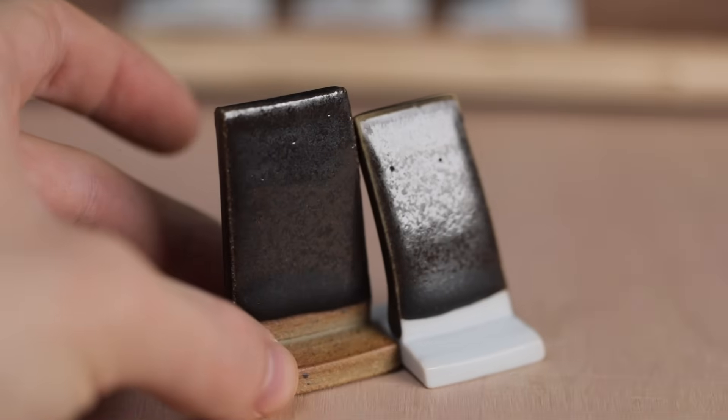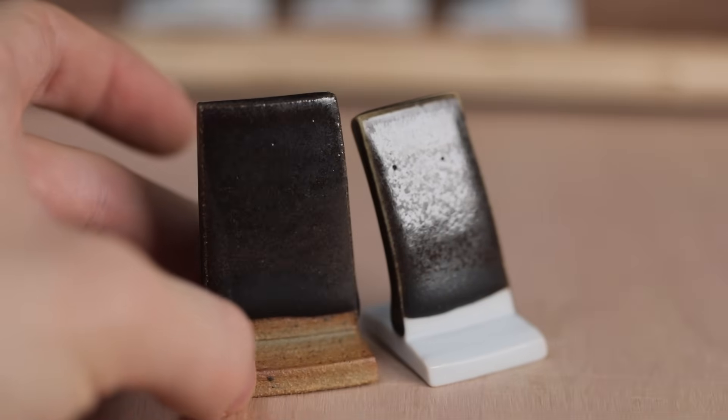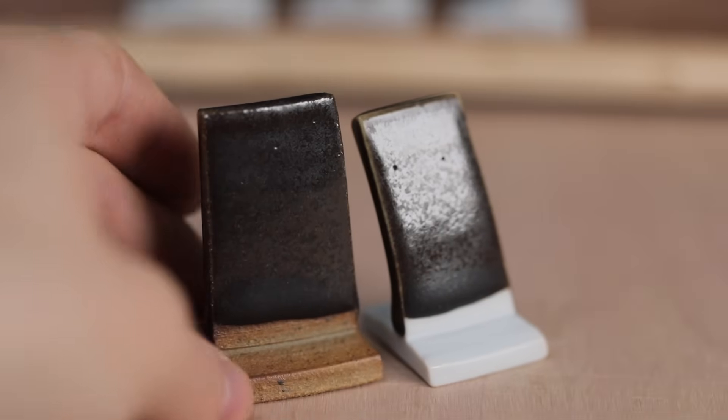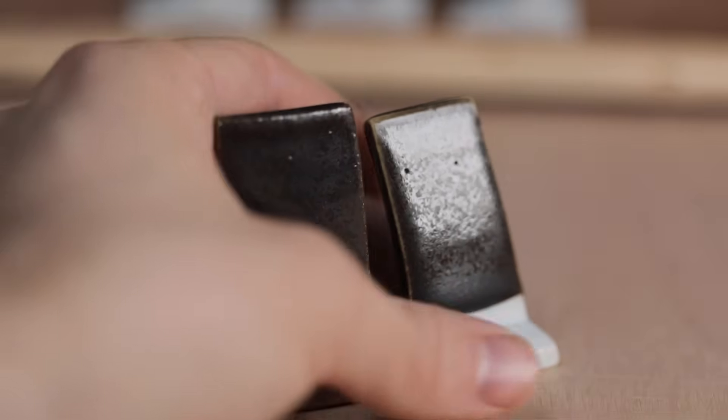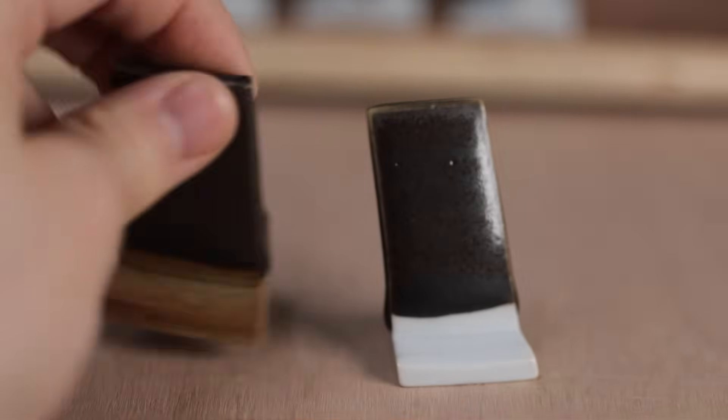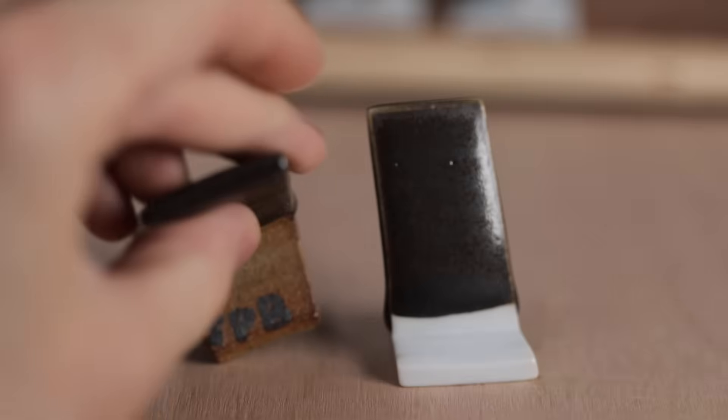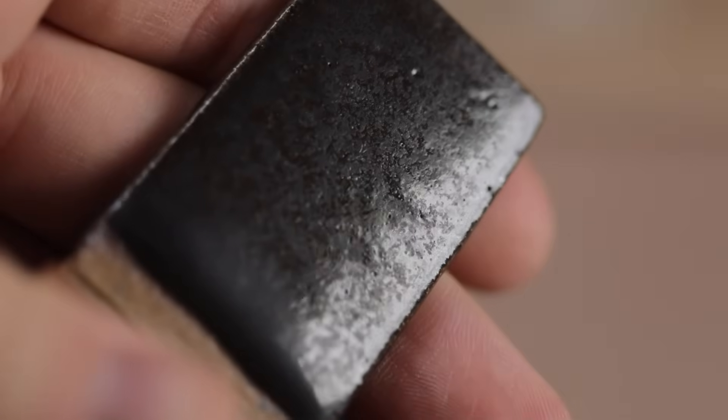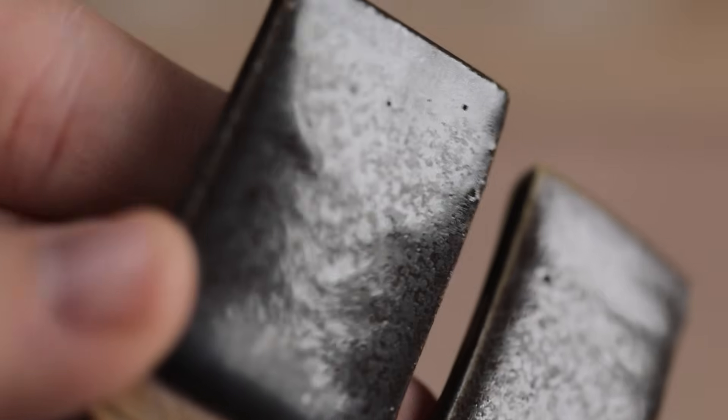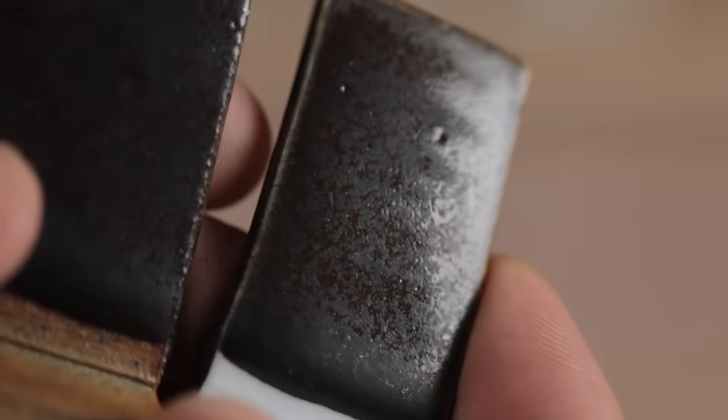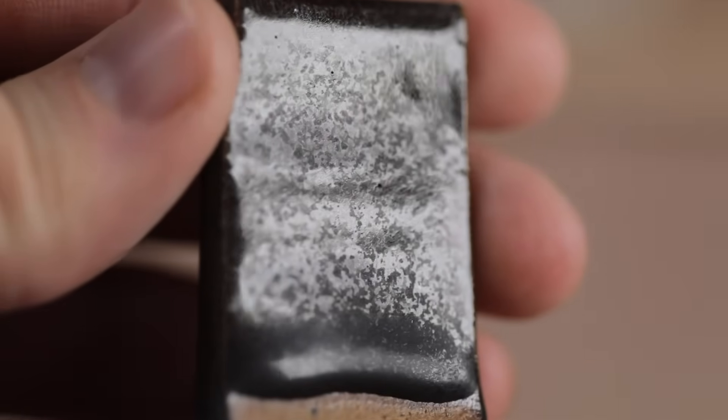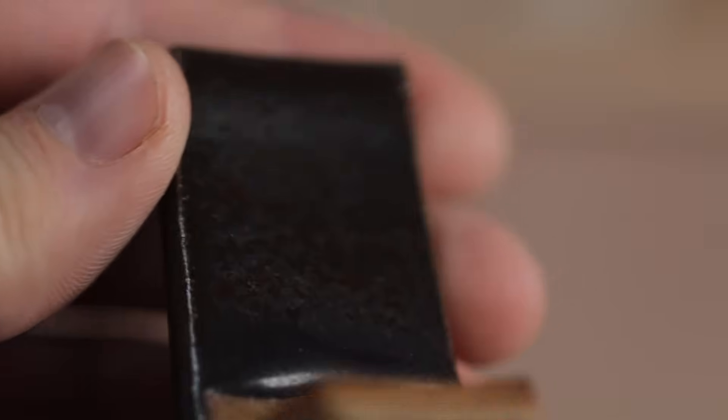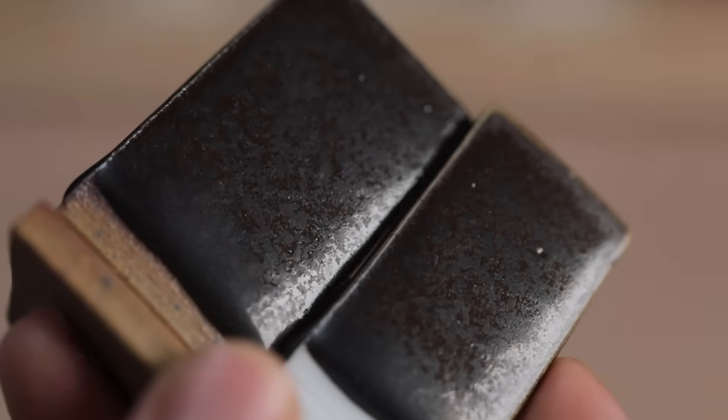And this one, which is actually basically the same glaze I mixed accidentally, replacing the black stain with red iron oxide, which was a total error, but it caused something rather amazing to happen. It's both glassy and matte, and has a rich red-brown undertone like rust. It shimmers, and is iridescent. It does have a few pinholes, which I'll try to resolve, but in the grand scheme of things, a few little specks like that really don't bother me. And I especially like how this glaze flows into a thicker band towards the base, which should look really good on a bowl form.